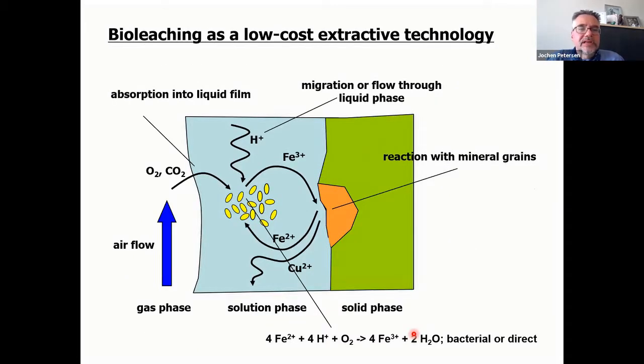The second technology I want to touch on as a potential low-cost extractive technology is the field of bioleaching. Bioleaching actually makes use of a whole host of different microorganisms that can facilitate the dissolution of minerals. Here the example just shows one of them, which is the ferric leaching of sulfide minerals that releases, in this example, copper into solution, and the reduced ferrous is then regenerated by microorganisms using oxygen that is absorbed from the gas phase. But there are many other microorganisms that can facilitate the dissolution of other types of minerals. And there is a substantial amount of research going on in that area, trying to understand them.